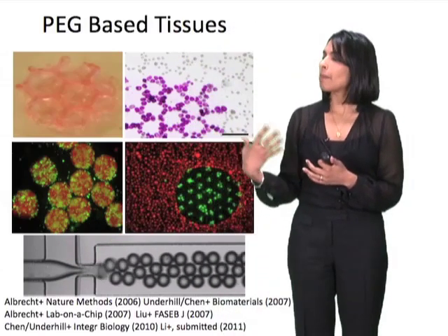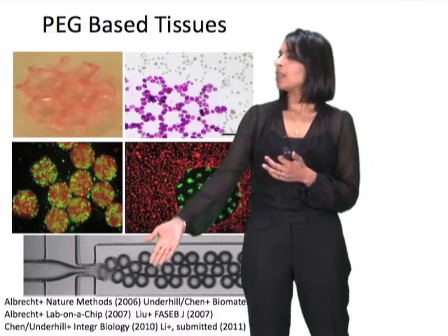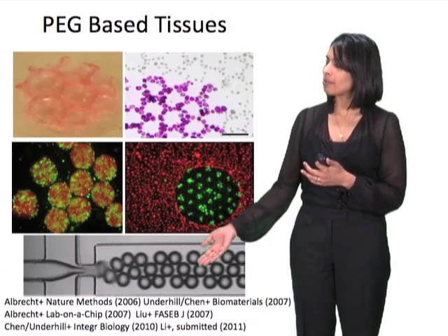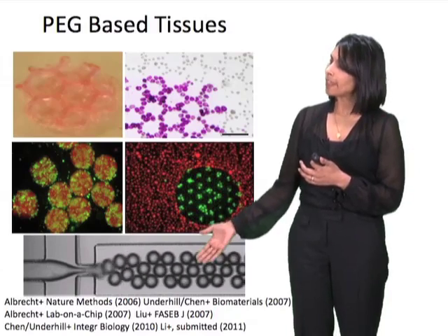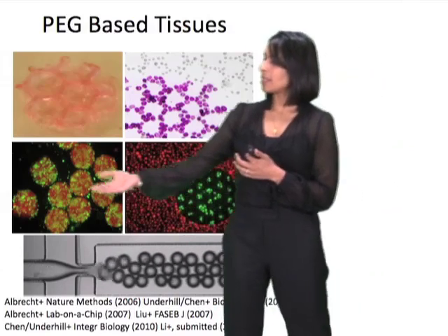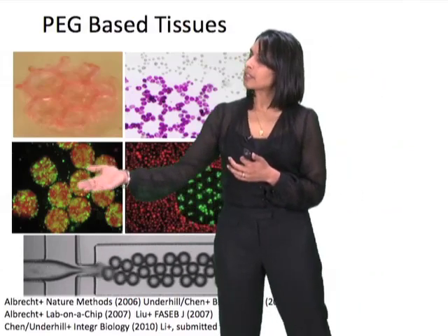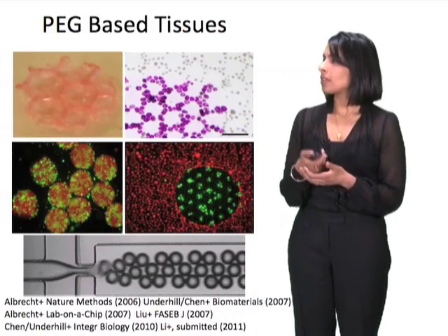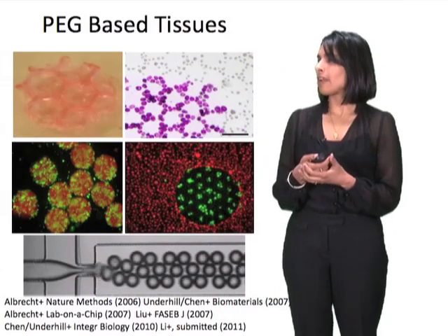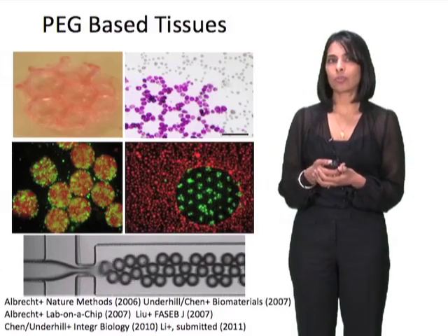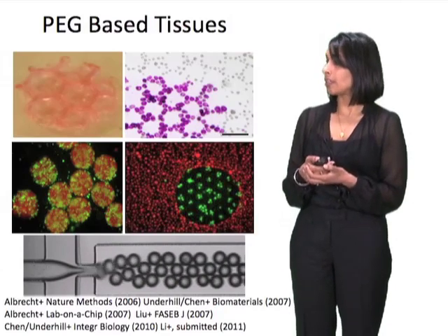And what you see entering into this microfluidic nozzle is a mixture of the cells and the polymer suspension. As they bud out into these droplets, then they are ready to have light shone on them, and then they can be polymerized in these microfluidic droplets. And this is an example of cells inside these microtissues. So we've made progress now on the fabrication of these hepatocyte-based tissues. The next thing we wanted to do was see how they would do in vivo.